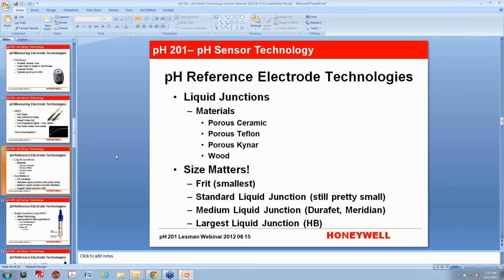of the junction itself. And that's important because, yes, you want to keep electrical contact, but you don't want process fluid to go into the reference area and mix with the potassium chloride in there, because it changes the voltage potential around the reference electrode, and that causes an offset in your sensor, and you'll see it as drift in your measurement. You keep calibrating down, down, but the sensor keeps going up, up, and that's a drift problem.